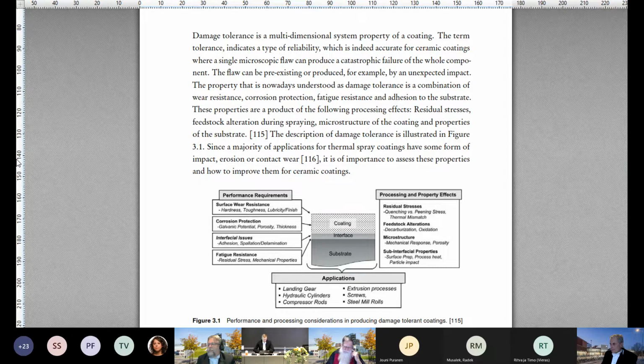Well, application-wise, I'm not sure right now, but based on some studies I read from CNRC from Canada, I think, they had sprayed with HVOF titania agglomerated sintered particles that had primary particles that were nanosized, and there was some unmolten particles in the coating that then acted as crack arresters. Because from the cohesive part, the dense part of the coating, you get a crack propagating, but it comes to this, that's essentially a discontinuity like a pore would be, but maybe not so undesired. And this nanostructure then stopped the crack. And I could imagine titania coatings like that could be interesting in sliding wear applications, anywhere where a titania coating would be used, but these would just be better.